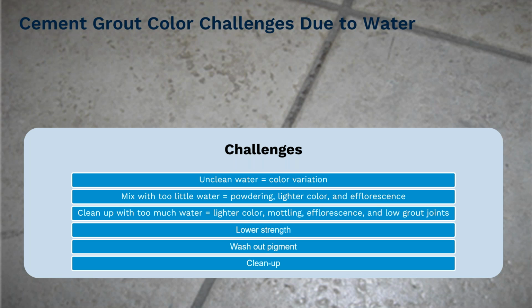As you can see, it is such a big challenge that I actually have a separate slide with that. So cement grout colors that have challenges due specifically to the water content. If the water is unclean, you can cause some color variation. Again, that comes with the contaminants that are in the water can affect the color. If you mix it with too little water, kind of like we said before, you get that lighter coloring, or you might have some powdering because it hasn't mixed the powder all the way through.